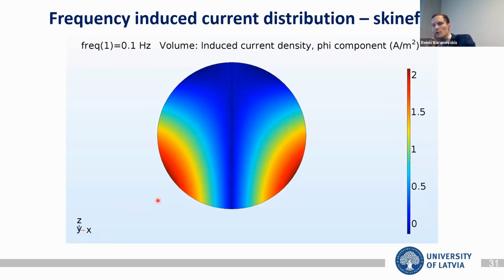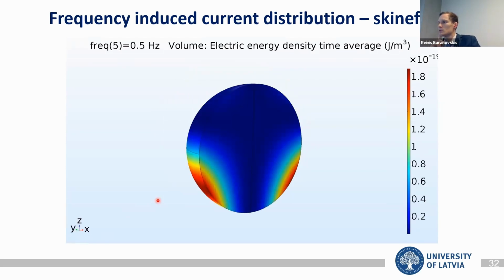And this becomes important since when something is trying to leak out, you have to understand that the size of the area where the electromagnetic forces are acting is determined by this skin depth and the skin effect. And if the droplet is invisible to the electromagnetic field, it will just leak out.